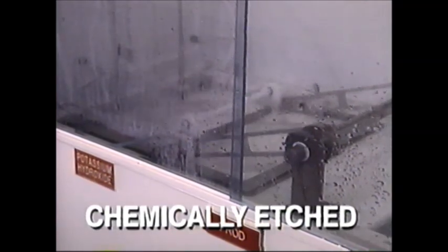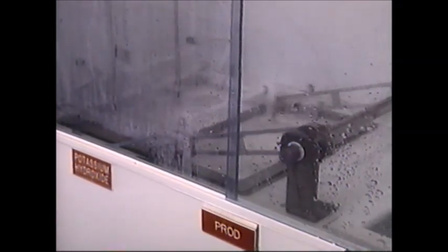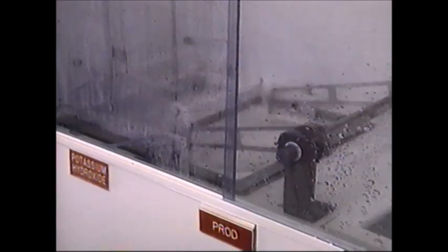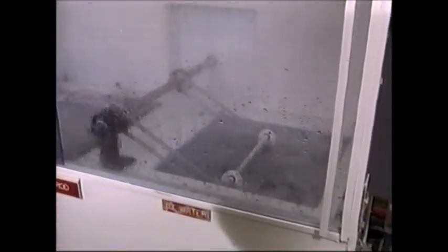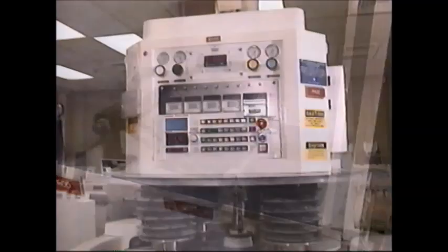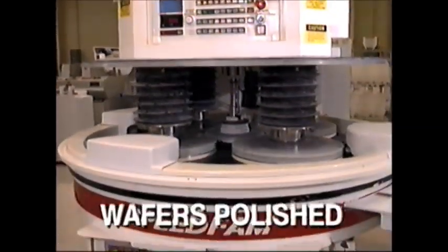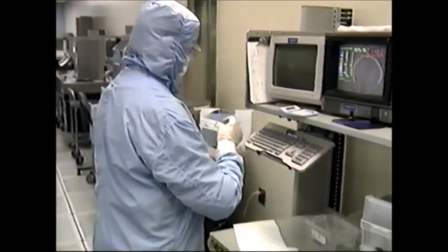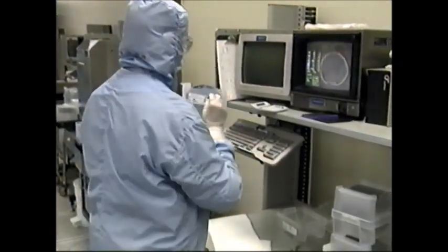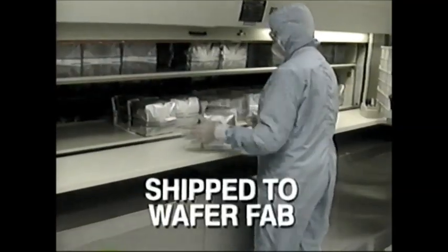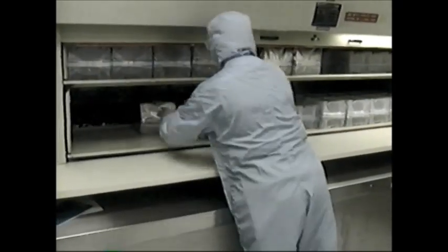After the lapping process, the wafers are chemically etched using potassium hydroxide to remove damaged layers of silicon. This step is critical because without this stress relief etching, the wafers would warp. Finally, the new cut wafers are polished with a weak caustic solution of fine abrasive slurry. After final inspection, the wafers are shipped to wafer fabrication facilities for further processing.